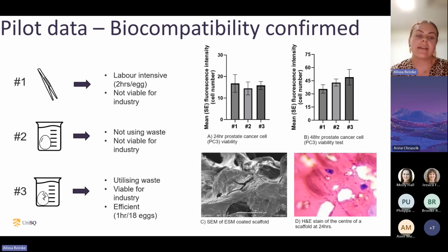So I started trialing different methods. I did try putting a whole egg into acetic acid, and that did dissolve the eggshell after about 2 to 3 hours, but it's then not using a waste product, and it's not viable for industry because you would need to buy a lot of eggs that would then just be wasted. So the final recipe that I tried was cracking an eggshell and putting the cracked eggshell into acetic acid, dissolving the eggshell itself, and then taking out the membrane. Now, this was very efficient. I could do the whole 18 eggs in about an hour, and it's still utilizing a waste product. And because it is efficient and easy to do, it is also viable for industry.